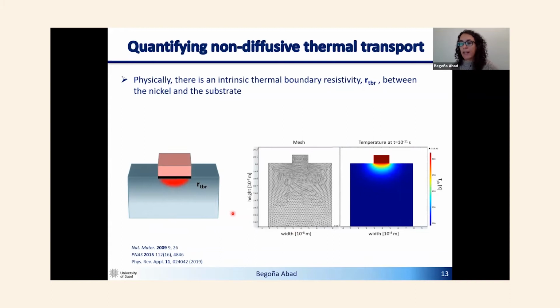So now I'm going to explain how we quantify this non-diffusive thermal transport, which is not trivial. So we relied on diffusive thermal transport. We use Fourier's law, which describes the thermal transport in materials. And what we have here is our nanoline on top of a substrate. And we do finite element simulations with our nanoline, and we create a temperature profile in order to fit our experimental results. So we know that between the nanoline and the substrate, there is a thermal boundary resistivity, which is intrinsic to every two materials that are put in contact. In this case, the nickel and the silicon.